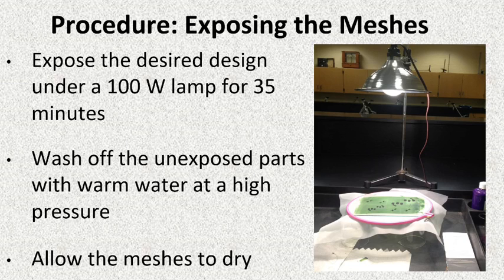Then, you actually want to expose it to light by placing the template that was made earlier with SolidWorks and expose the desired template under a 100-watt lamp for about 35 minutes. This causes the photo emulsion fluid that has been exposed to light to harden, but the stuff under the templates will not harden. And so it's much easier to remove, and you remove those unexposed parts with warm water at a high pressure and allow these to dry. And that is how you make the stencil.